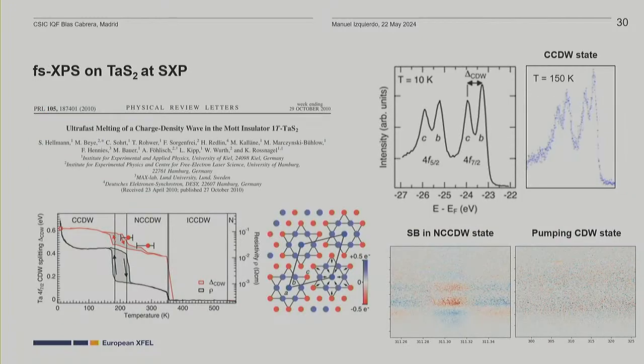So basically we did femtosecond XPS on tantalum disulfide. And this system is very interesting because it has a very interesting phase diagram as a function of the temperature. So basically at low temperature you have a commensurate charge density wave. Around 200 Kelvin this changes. And then at room temperature there is a nearly commensurate charge density wave that above 350 evolves into an incommensurate charge density wave.